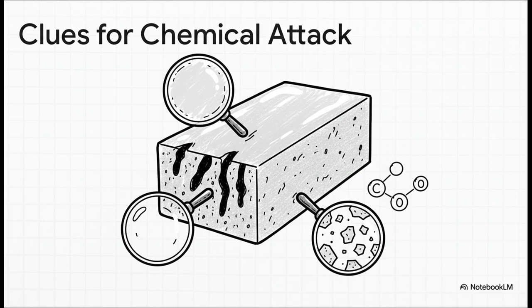Now, the clues left behind by a chemical attack are way more subtle. You might find this glassy glaze layer on the surface, but sometimes the attack is even more clever. Carbon monoxide gas can actually sneak into the pores of the brick and cause it to crumble from the inside. Or, even worse, chemical reactions can create new liquids that have a super low melting point, basically poisoning and weakening the refractory structure from within.